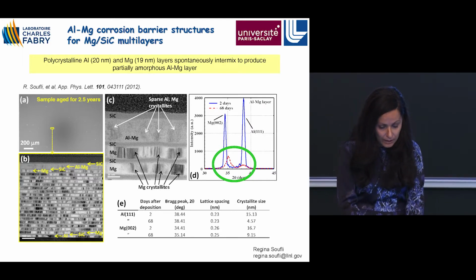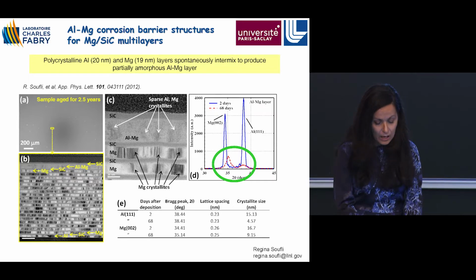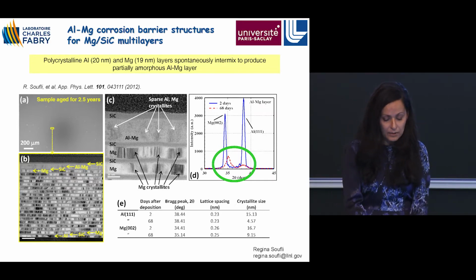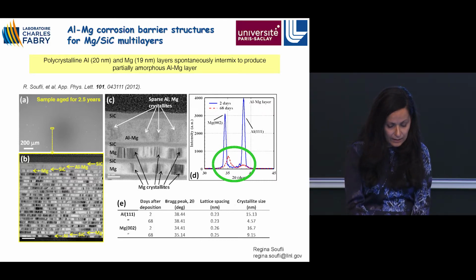I'm going to show you here the amorphization of this coating. Here you can see the magnesium and aluminum diffraction peaks of the coating just a few days after deposition, and in the red curve, which you probably can see is a little bit faint, you can see that a few weeks after deposition, these peaks are almost gone, again demonstrating the amorphization of this coating.